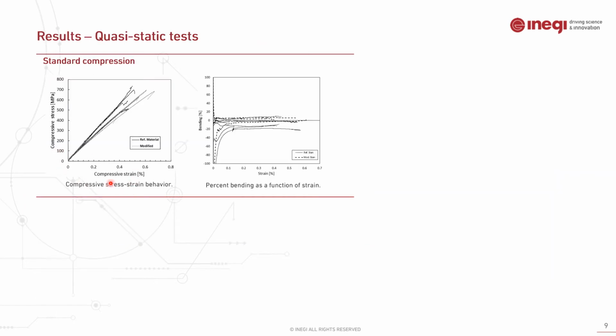Here you can see the stress-strain behavior of both material configurations, performed based on the ISO standard. At first glance, you can notice that there is a notable decline in the stiffness value of the modified materials. And over here on the right, we have percent bending as a function of longitudinal strain. As you can see, the bending behavior appears to be mostly within plus or minus 20%, except for two experiments that are slightly exceeding these limits.